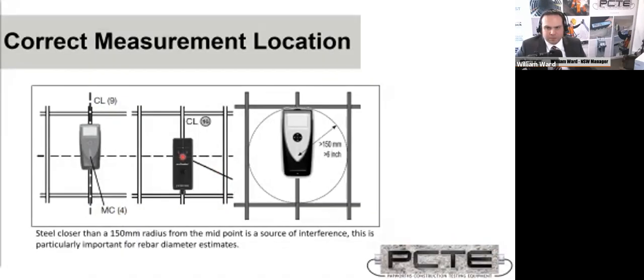So on a Profometer, that is usually centered on your midpoint line on the probe here in the standard and extended to the long measurement range of a Profometer probe. There is a spot measurement mode, which I won't go into detail for, but its center point is measured at the closed circle towards the top of the probe. The open circle is the regular measurement point on a Profometer probe. On a Profoscope probe, you measure in the crosshair, which is normally under your hand, below the screen, below the buttons.